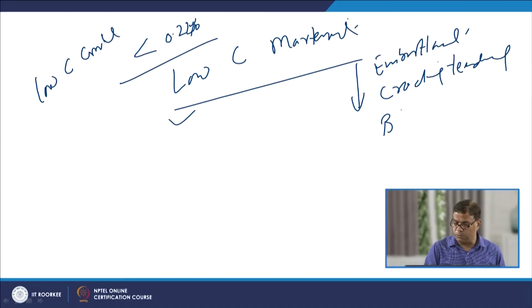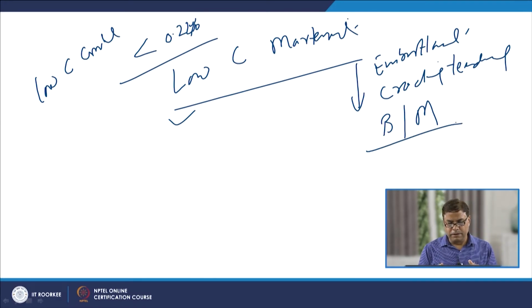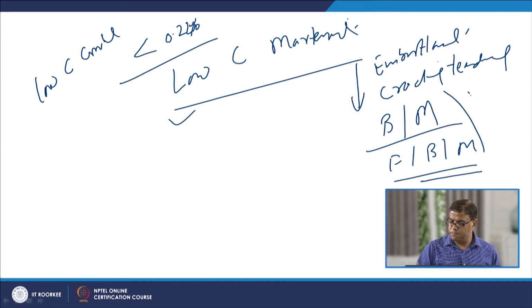Primarily these are designed to have the bainite and martensite, but there are certain compositions where it can have the ferrite, bainite and the martensite. So, as per the kind of heat treatment conditions and the tempering conditions which are being imposed, it can have the high carbon martensite or the low carbon martensite, upper bainite, lower bainite, etc., which will be leading to different combinations of properties.